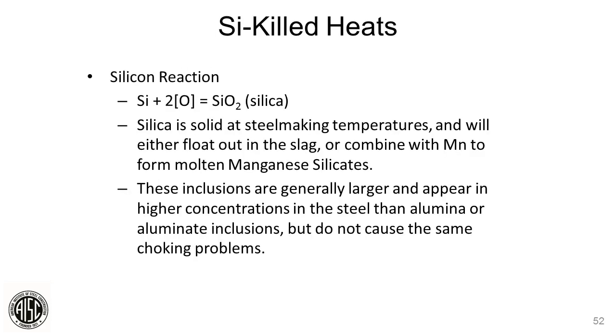Simple silicon reaction: silicon plus oxygen grabs 2 atoms of oxygen, makes silica sand, which floats to the top and gets sucked up into the slag, and it's gone. If it doesn't get out, it does make inclusions. You'll hear about inclusions in steel. We can't get all of them out, but you get most of them out. And aluminum is very hard to do because you've got to be very careful with it. You can cause casting problems, and we call it choking, where it'll terminate the cast, and we don't want to do that either. So next slide, please.